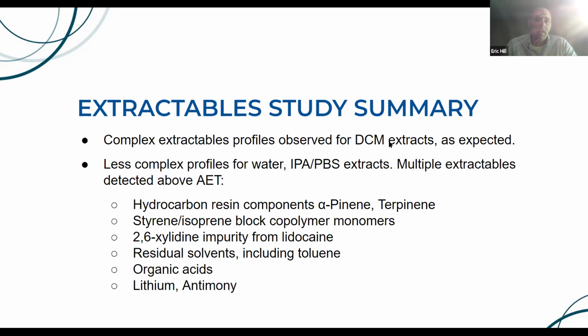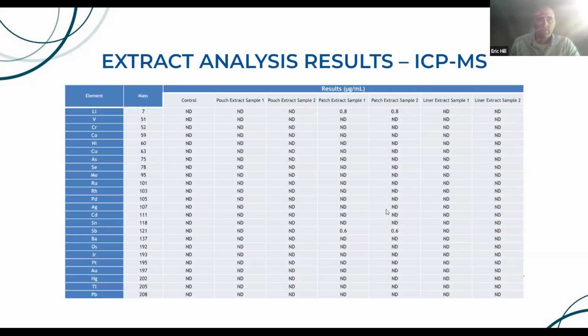We saw the 2,6-xylidine impurity from lidocaine, as the FDA directed us to look for and as expected. We saw various residual solvents, including toluene, organic acids, and then we saw some lithium and antimony in the inorganic analysis. And this is a table of that inorganic analysis. Again, you can see the antimony as well as the lithium. Other than that, it was very clean.